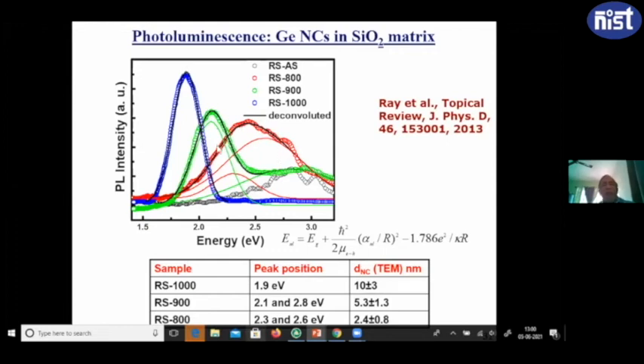When the size of the nanocrystal was very high, or there was some defect, this germanium nanocrystal shows some emission in the red region, which is very broad. When the nanocrystal size was reduced, it became green. And when it is further reduced, you get blue light emission from germanium. And as you see, this emission takes place in the visible wavelength range, and at room temperature. This is one of the ways to get light out of germanium quantum dots.